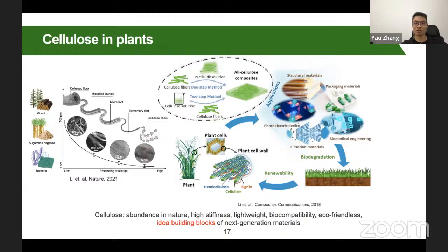I think the diameter of one cellulose microfibril is around three nanometer. This cellulose is the most abundant in nature, and it also has very high stiffness. I think you may know that. Its stiffness can reach a theoretical value of about 200 gigapascal. It is also lightweight, biocompatible, and eco-friendly. So it's an ideal building block for next generation materials.